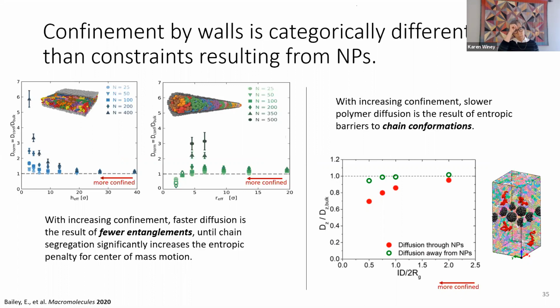So just to wrap up the chain diffusion from the simulations, in confinement, more confined, because you're decreasing the number of entanglements, you get faster diffusion until you've confined things so much in the cylinders that they become segregated, and then things get much slower. And it's really quite different in the nanocomposites. Even with the monolayer, we can see that there's a long-range effect of the nanoparticles on polymer diffusion. The nanoparticles are slowing down polymer diffusion, even far away from the particles. And overall there's this anisotropy, so moving towards the particles is a lot slower than moving away from the particles.